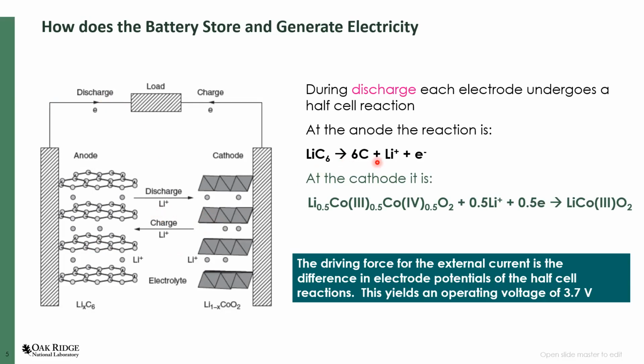So during a discharge, for example, in this case, is this famous lithium cobalt oxide, which was discovered as a battery material by Professor Goodenough, and carbon, which is the intercalation compound. So you can write these reactions that take place in these two parts using these half reaction models, where lithium C6 goes to carbon and a lithium, and at the cathode you have the lithium cobalt oxide, in this case with lithium of around 0.5, going to lithium cobalt oxide. And it is the difference in the electrode potentials of these two half reactions which yields an effective operating voltage.